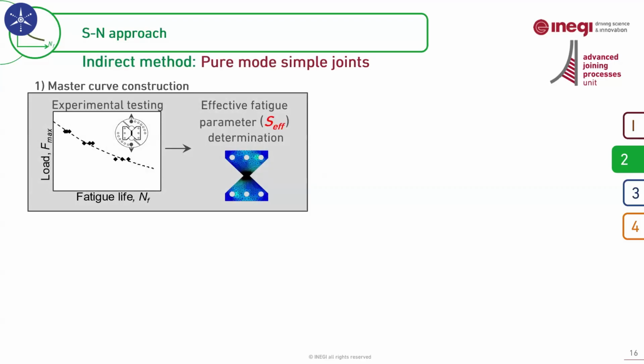On the other hand, we have the indirect method. From the experimental perspective, the key difference in the indirect method is that you must test simple bonded joints under pure loading modes: pure mode 1, pure mode 2, even pure mode 3. So, for example, a single lap adhesive joint is generally not suitable for this approach unless under some special conditions. In our work, we have used the Arcan specimens for this purpose. This specimen meets the requirements for fatigue analysis in bonded joints. Arcan has the advantage that you can change the loading angle without changing the specimen geometry, the setup, the boundary conditions, or the joint type.